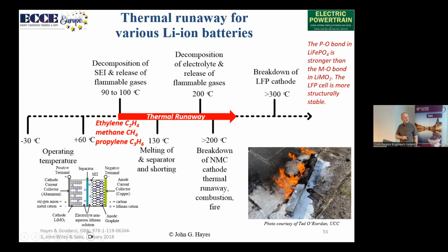and we will get fire and explosions. And the big benefit that LFP, lithium iron phosphate, has is this, the equation for this iron phosphate, the PO4. That's a relatively strong bond between the metal and the oxygen, and it's a higher temperature before it breaks down and releases the oxygen. So that's why LFP tends to be a safer cell than the nickel-based cells.